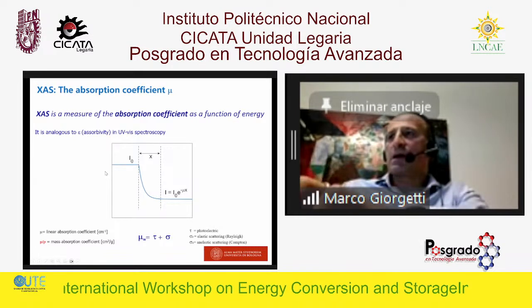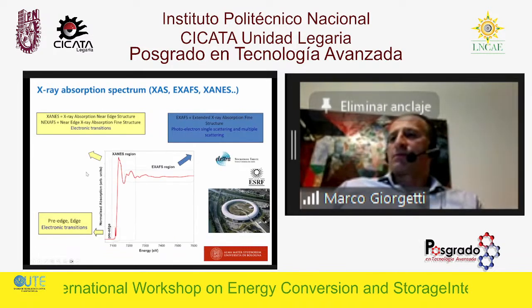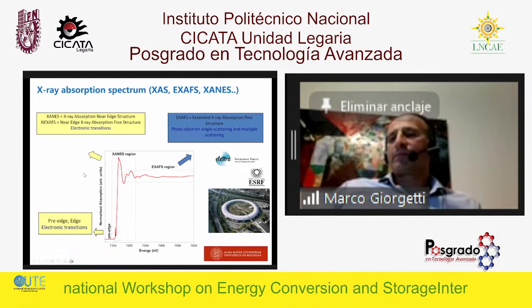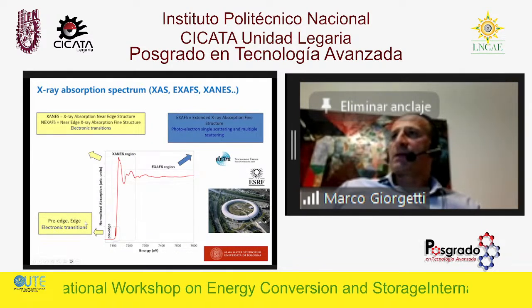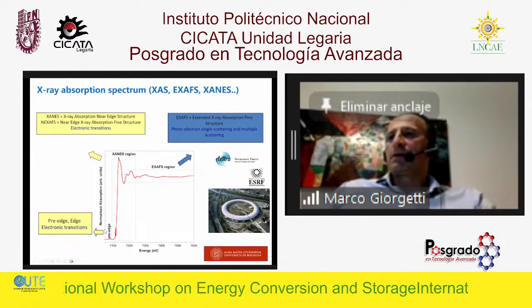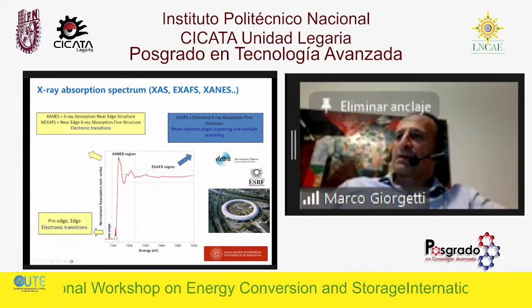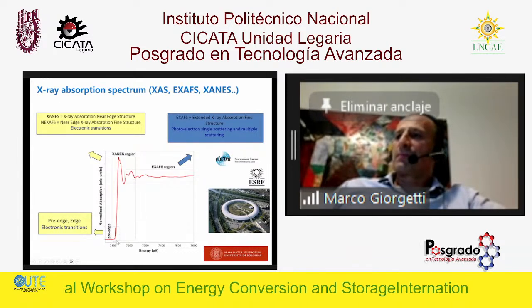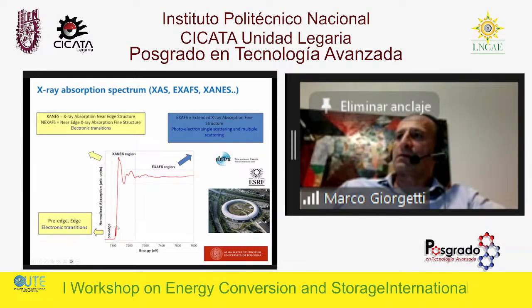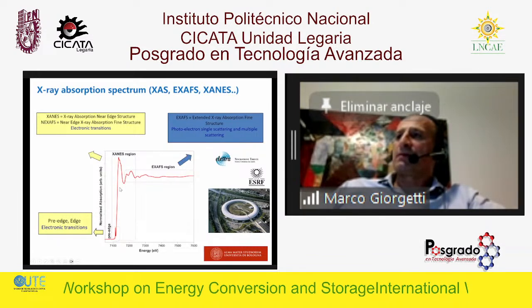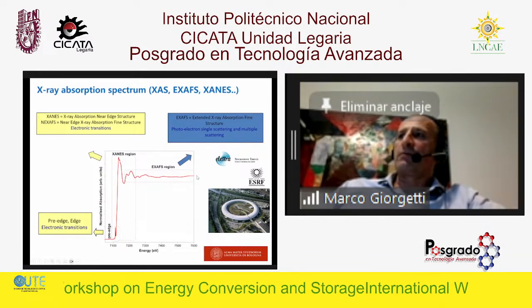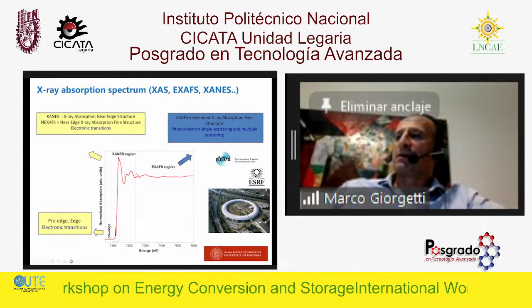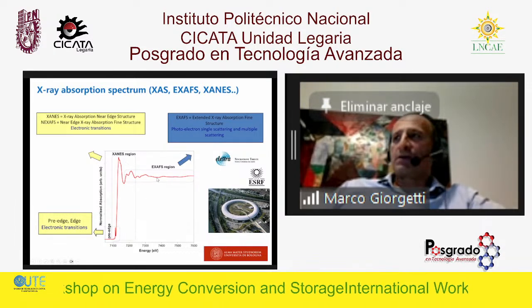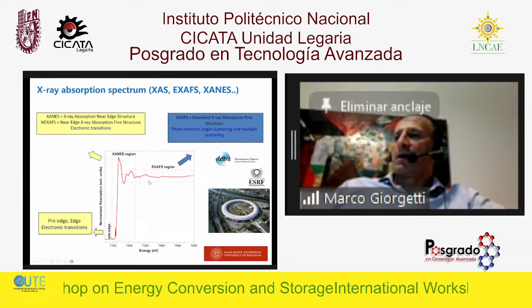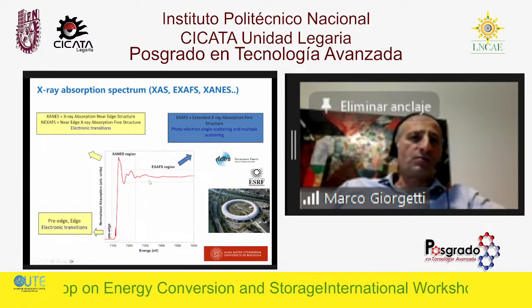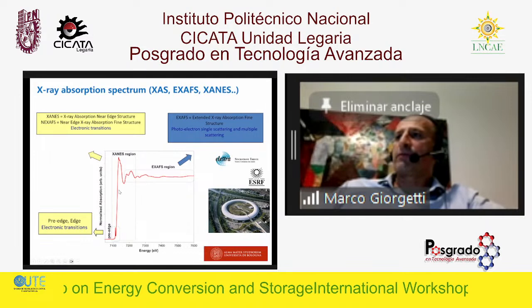And you are going to see now one experiment. Basically we have this rising-up feature here as a function of the energy. Here we created a core hole. And instead of having a linear behavior, you have a lot of features here, features that are very interesting for us. And we can divide them into three main regions, even though here we created the photoelectron.